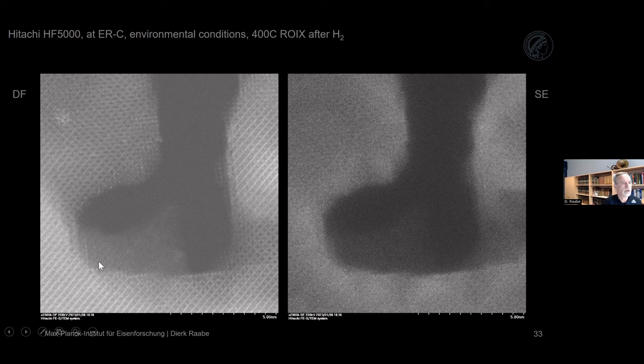Here we go to the high resolution, to atomic column resolution in the environmental microscope. That is quite challenging to do. And you see the first pores, where the mass loss occurs, where the individual oxygen vacancies collapse to form nanopores, and they grow a little bit bigger. You see also where the first iron nuclei are forming, but we are still busy with the analysis of these pictures. So for these pictures directly, you cannot interpret too much. There's a lot of follow-up analysis to be done.